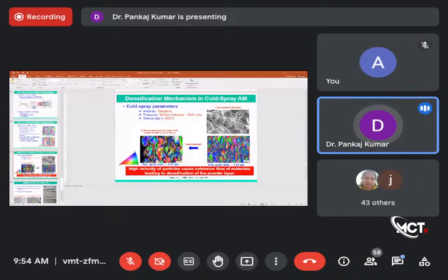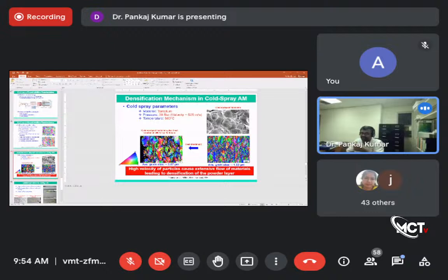At the interface, if you look, these are the interface. So at the interface, you have the very fine grains, right? Those grains actually tell you that the interface is metallurgically bonded. So they are very strong. The layer itself is very strong. You cannot just simply break it. Okay, just like a complete metallic structure. And when you heat treat it, your average grain size changes. Of course, you expect grain size to change. So the idea is you can optimize the grain structure, but your surface roughness is another issue that we really need to worry about.